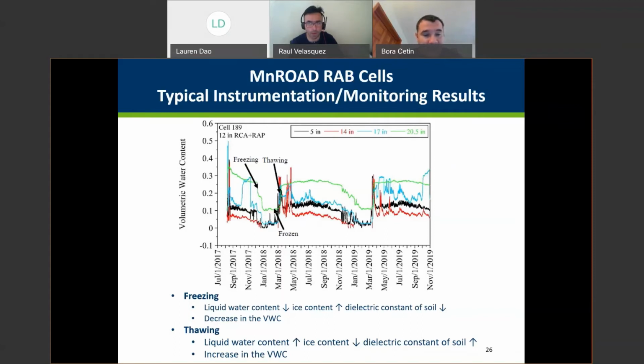And then when you come to March, as you can see, we see that steep increase in the volumetric water content, indicating that the formed ice starts melting and then fluctuates or stabilizes over time. Why we show this graph is that we will show the thermocouple readings. We use the volumetric water content to confirm that the soil is really frozen when it is below 0 degrees Celsius, because you see a sudden decrease in the water content measurements, indicating that water is also freezing. And we use the volumetric water contents and thermocouple measurements, which I'll show you in a bit, to determine how long the soil stayed frozen, and how long it takes for the entire depth to thaw.